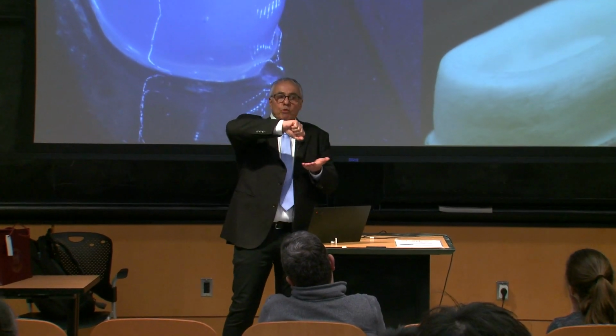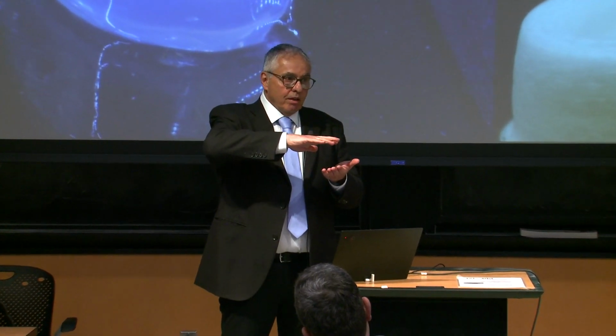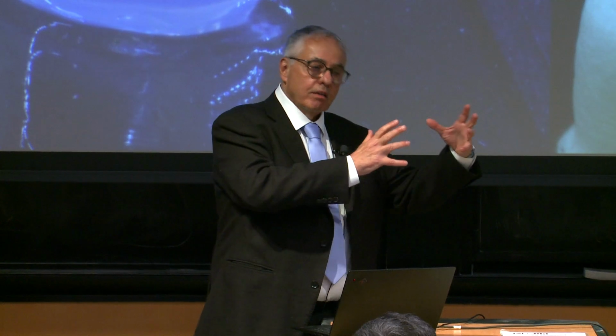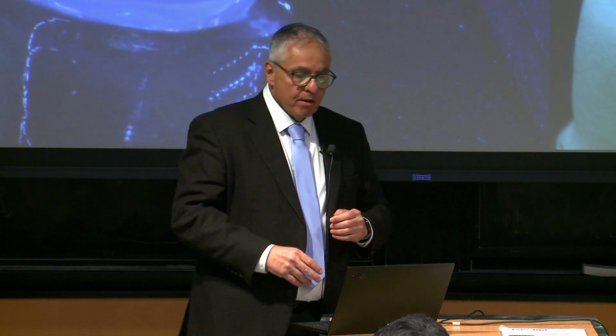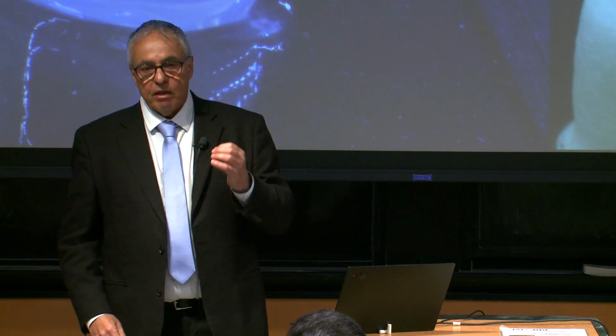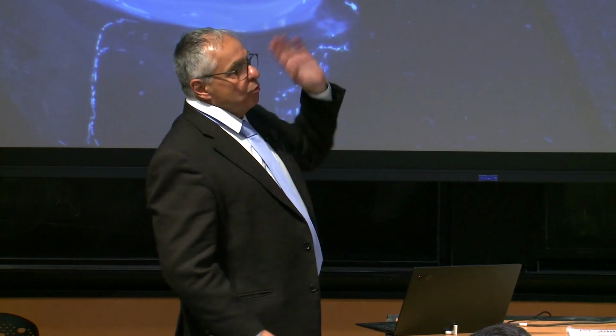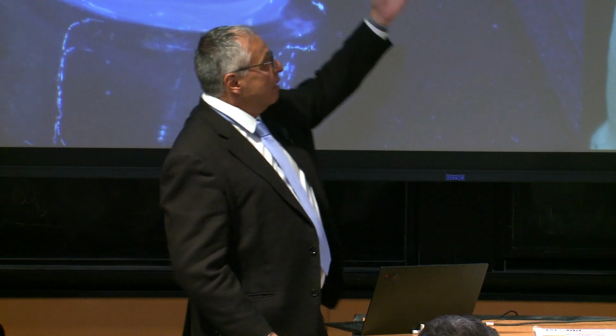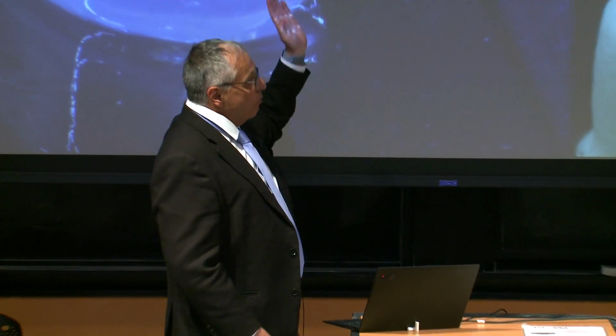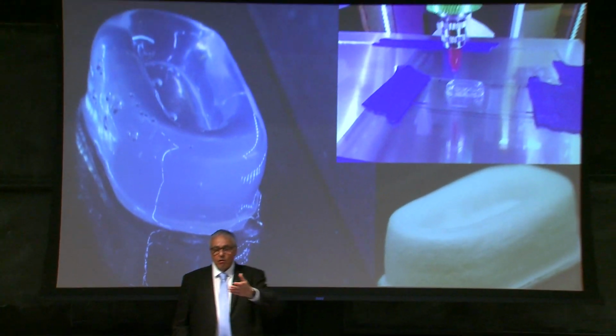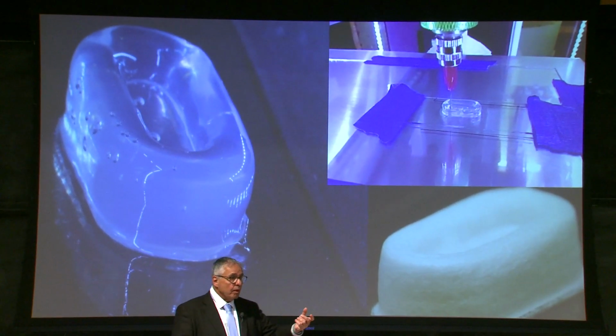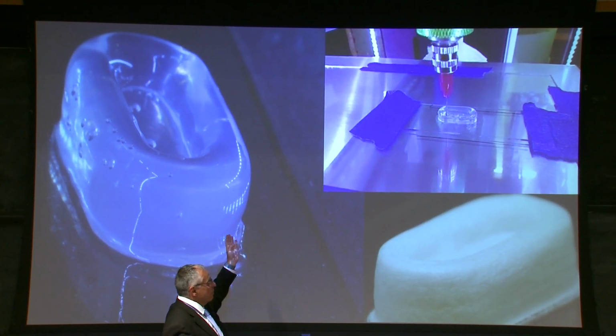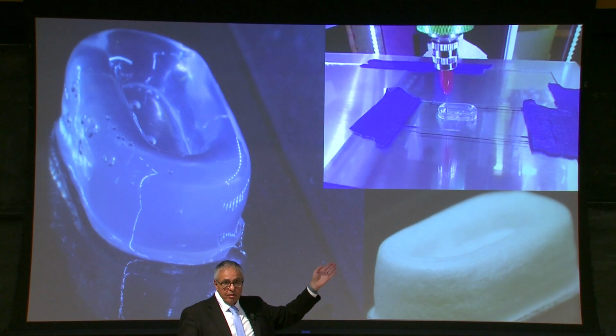But once we apply it on a sandwich, for example, something really nice happens. It doesn't drop. It stays there. Why? Because the shear force is not there anymore, so the viscosity goes up very, very quickly. That's the beauty of cellulose nanocrystals. It's a very, very thixotropic material. That enables us to take only 3% cellulose nanocrystals and 97% water, and put it in a syringe.